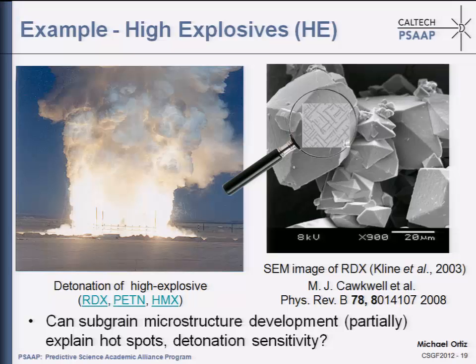So when you look at individual grains, you find that the deformation is far from uniform, but it can localize along very narrow shear bands. Those shear bands actually deform much more than the average deformation of the material. You develop very high pressures there, very high temperatures, so you have hot spots. And so initiation, of course, is all about developing hot spots. It's no longer just about average conditions in the grain, but the extremes of the distribution.